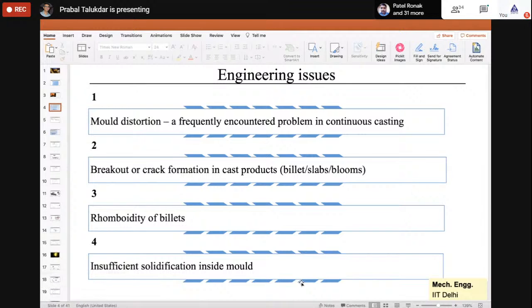And the other issue is insufficient solidification inside the mold, right? If the solidification doesn't happen properly inside a mold, then the strand formed at the outer periphery, that small, thin solidified strand formed inside the mold, will be very thin. And since it is very thin, when it comes out from the mold, there is a possibility that it will break. And if it breaks, there is a problem, because once it comes out from the mold, there is no guidance. It is basically freely going out of the mold, and then you are spraying it. So that is why insufficient solidification is another problem. Of course, insufficient solidification basically brings out crack formations or breakout, whatever happens.